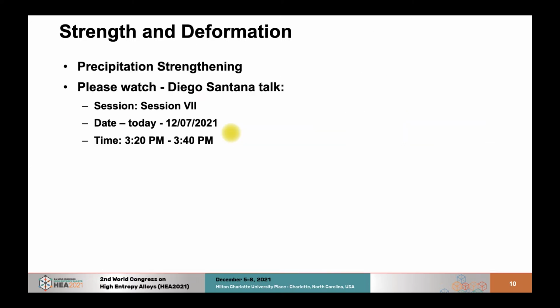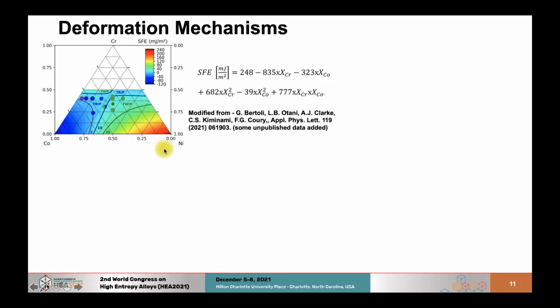I'm not going to talk in this presentation a lot about precipitation strengthening. I would invite everyone to watch Diego Santana's talk. I'm going to move on to deformation mechanisms. That's another very interesting topic of these alloys. So by changing compositions, we can go from dislocation glide only to TWIP effect and TRIP effect. So this figure was plotted using this empirical equation for stacking fault energy proposed by Gustavo Bertoli, and by fitting about 20 experimental data points of stacking fault energy.